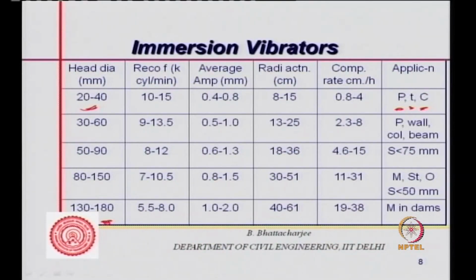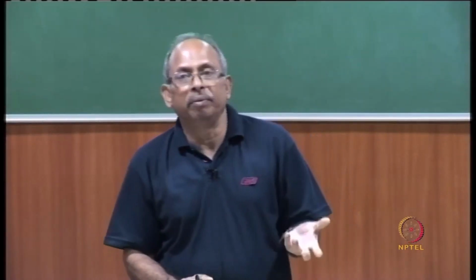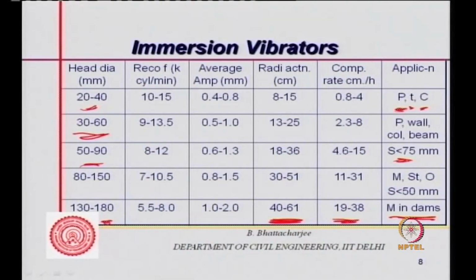While this might be used in mass concrete, you can see its radius of operation is quite high, and the compaction rate is also fairly high. So where you have large mass concrete, of course you want to vibrate it, then you might use this massive section type, for example in a dam. M stands for massive concrete, so mass concrete in dams. In between, 30 to 60, very common is about 60 mm. Slump less than 75 mm is suitable for that kind of concrete, relatively stiff, not very stiff. This is absolutely plastic, maybe 100 mm slump or less, just below pumpable concrete. Pumpable concrete is quite flowing, but if you are compacting it, you can use this also. But in thin sections and larger sections, of course, you can use this one.